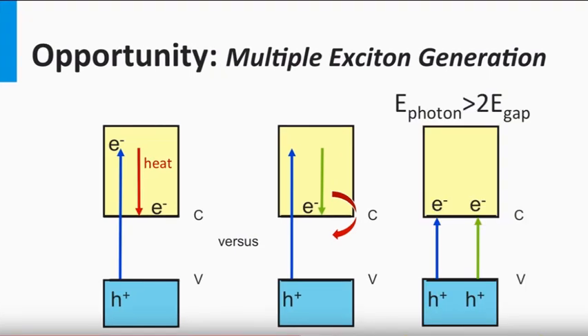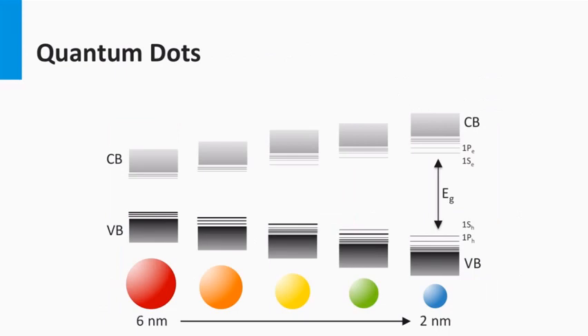A second electron can be excited into the conduction band. It means that the energy in one photon results in two excited electrons. The requirement, of course, is that the energy in the initial photon is at least two times that of the band gap energy. In this way, a theoretical EQE of 200% can be achieved as well. If you would have a photon with an energy larger than three times the band gap, a theoretical EQE of 300% could be achieved. Both for down conversion and multiple exciton generation, nanostructured semiconductors are studied and developed.